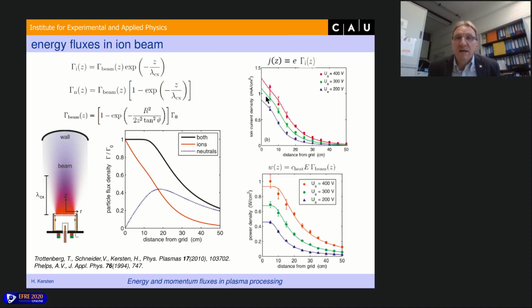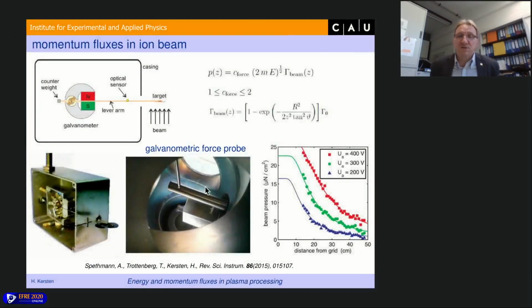And that means the advantage of our probe is that you can also measure neutral particles, fast neutral particles, for instance. Here we measured the axial ion current profile by the Faraday cup, and you can really see this profile. It's really by the ions. But if we measure the power density with our thermal probe, then we get such a profile. And this is the profile of both the ions and the neutrals. So this is really a very nice method.